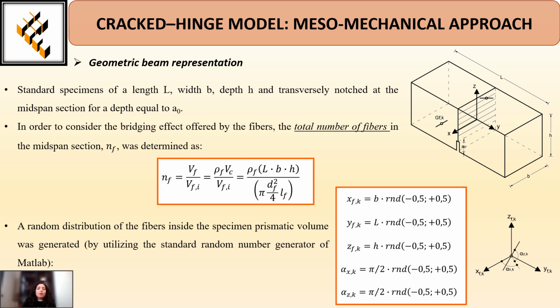In particular, the model is able to consider the bridging effect offered by the fibers, so the total number of fibers in the mid-span section was determined as the ratio between the volume of the total fibers and the volume of the single fiber. In particular, a random distribution of the fibers inside the specimen prismatic volume was generated by utilizing the standard random number generator in MATLAB.